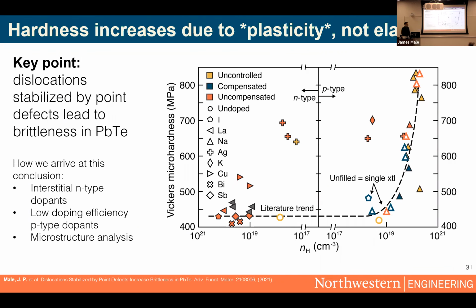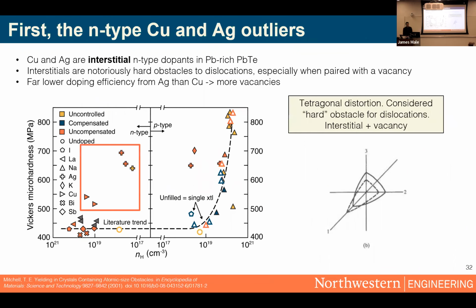I should also mention right off the bat, I have both single crystal and polycrystalline samples here. Single crystals are filled with white. So obviously grain boundaries are not the main driving factor of mechanical properties here. And I should also note that the ionic radius mismatch didn't appear to be the main driving factor as well. Instead, we see these other clues such as the effect of doping with an interstitial dopant in lead telluride.